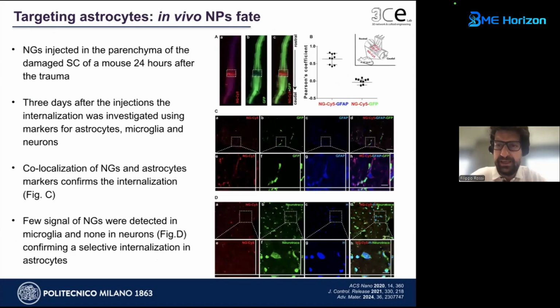These are the results obtained in vivo, and you can see that nanogel injected in the parenchyma, 3 days after the injection, is internalized mostly within astrocytes with respect to microglia. The colocalization obtained between nanogel and astrocytes confirmed internalization, and only a few nanogels detected in microglia and none in neurons confirm the selective internalization by astrocytes.